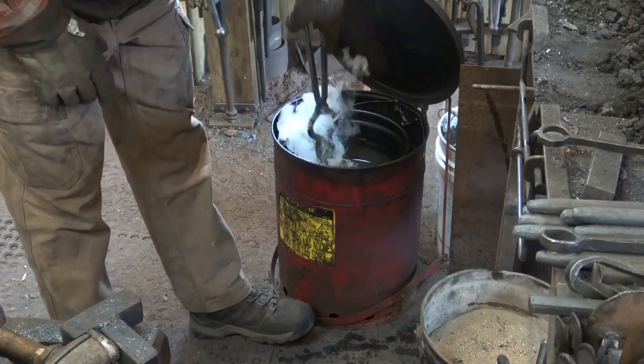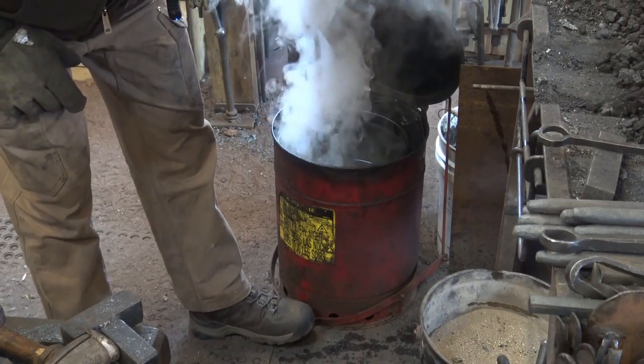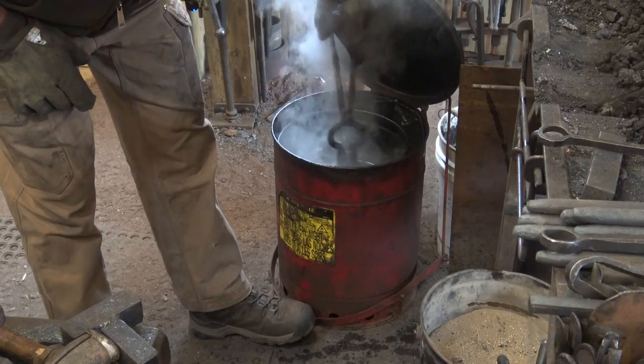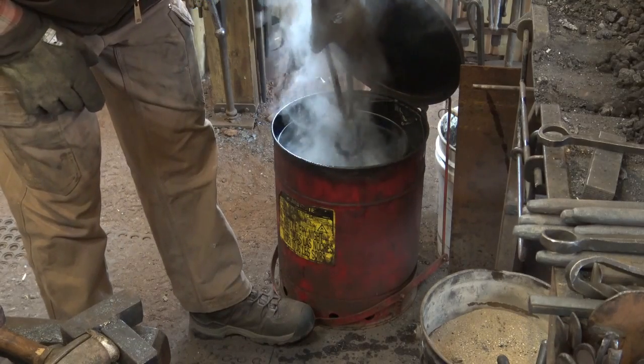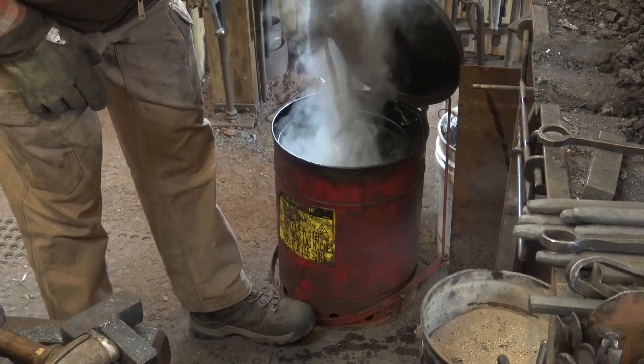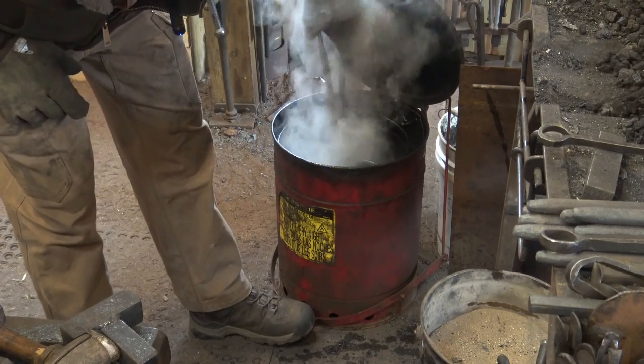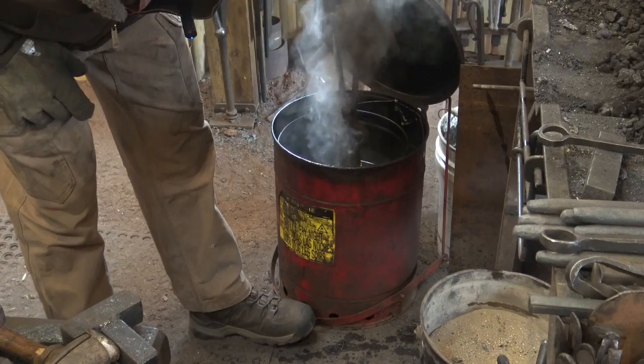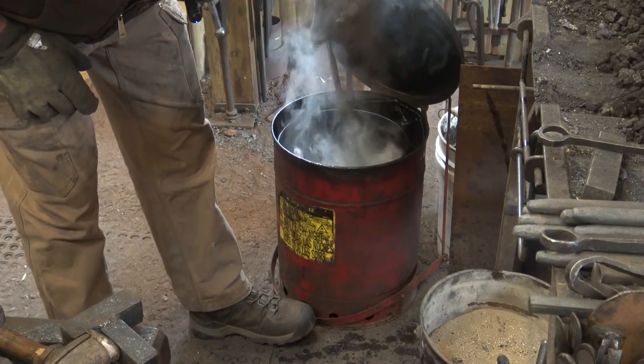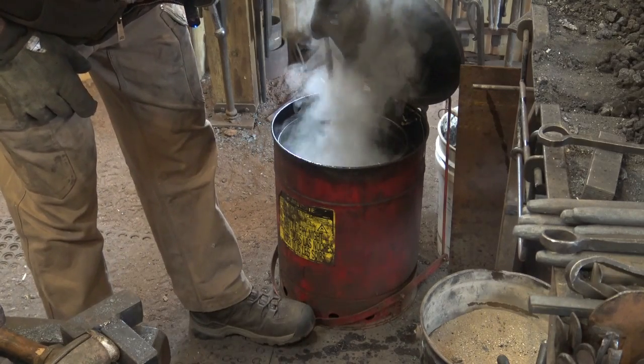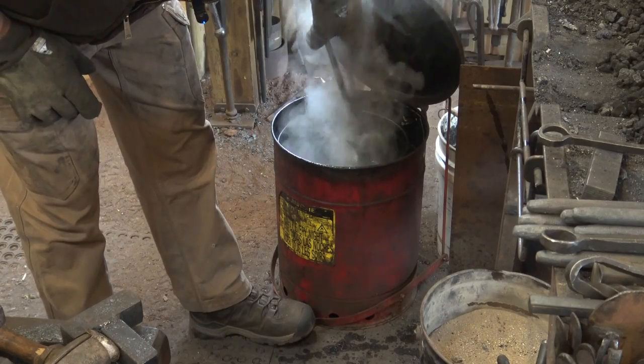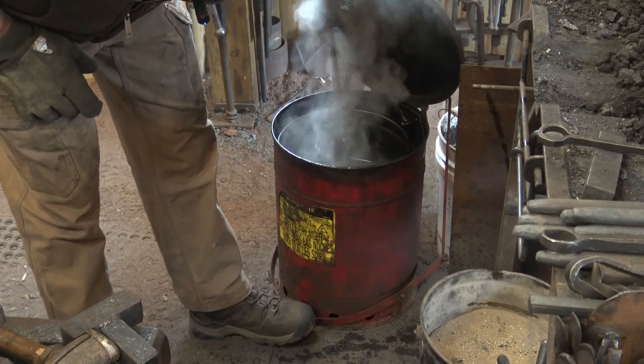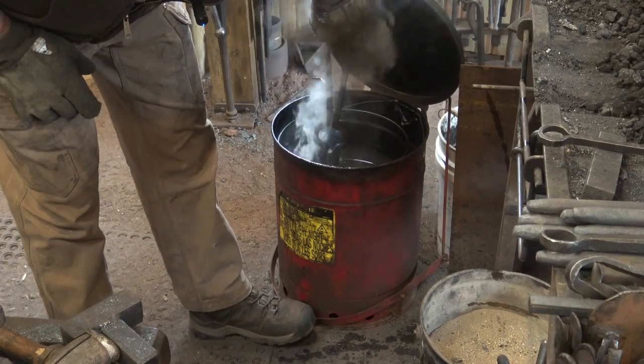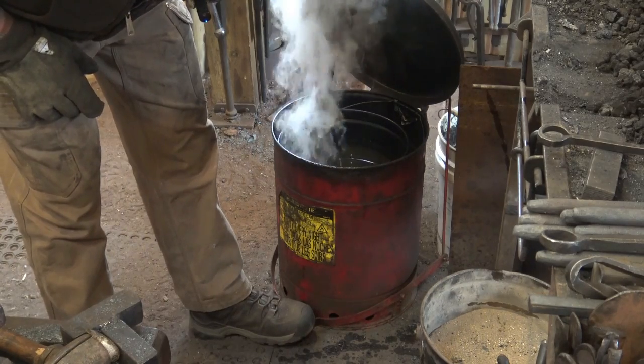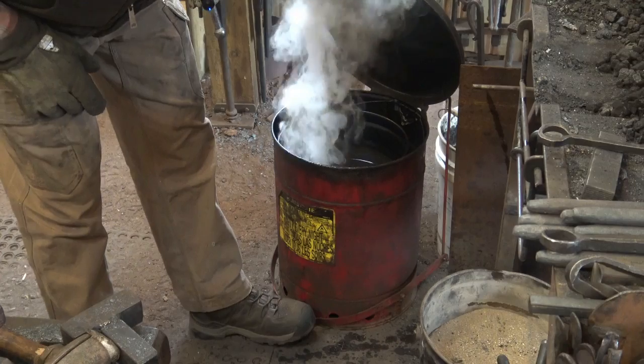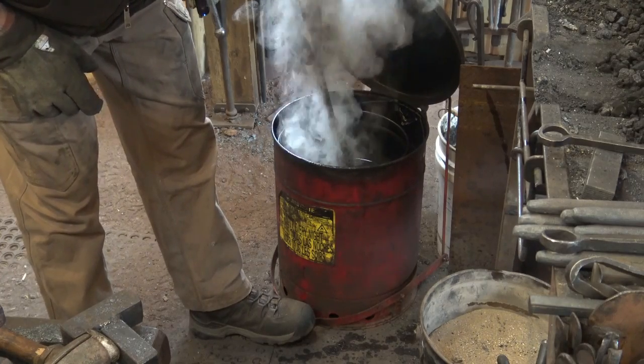We're going to quench it in the oil, same thing, up and down. Now I prefer to do this over by the door with the doors open and a fan blowing the oil smoke out. So I get my head way down so I'm below the level of the smoke. It's also why I would prefer to only work with water hardening steels. It just doesn't seem possible. Too many good steels are oil hardening. 4140 and 5160 in particular.